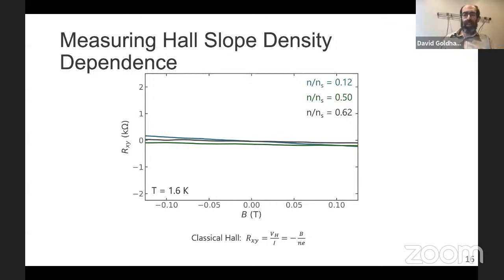And then at 3 electrons per moire, something changed. This was really quite striking. Now the Hall slope is quite steep. It's going up in tens of millitesla, up to a couple of kiloohms, a very substantial resistance, and it's not linear. It's now plateauing. So Aaron was disappointed that he wasn't seeing superconductivity in this sample, but he thought this was interesting enough that it was worth cooling the sample down to lower temperature.